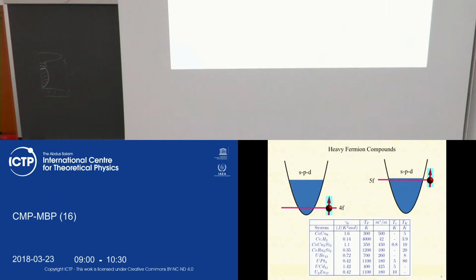The difference between these two families is in the position of the localized level, which is singly occupied. For cerium-based systems it is the 4f orbital, for uranium-based systems it is the 5f orbital. The position of this f level is related to the position of the Fermi level. In cerium-based systems, this localized level is far below the Fermi level. Therefore, there is no hybridization between these electrons and itinerant electrons, while for uranium-based systems, this f level, which comes from measurements and calculation, is very close to the Fermi surface. So there is very strong hybridization.